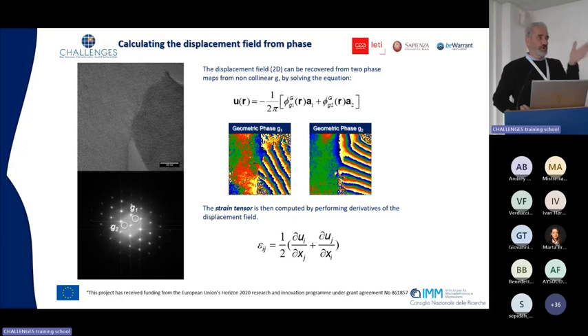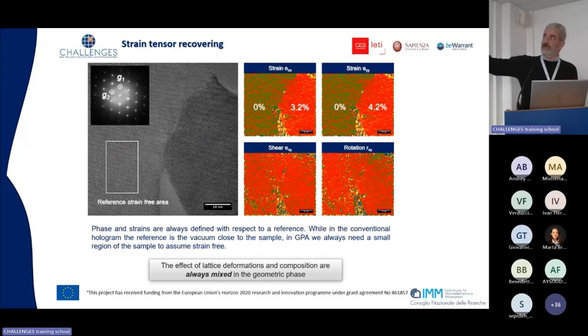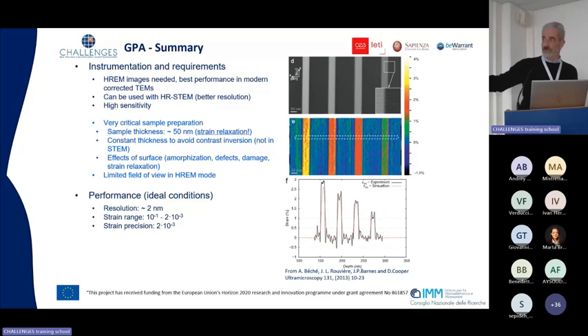So if you are able to collect high resolution images of the reference crystal and the strained crystal, you can use this method to extract the strain arrangement in your material. Okay, this is just a map representation of strain along X and Y and the shear strain, but this is straightforward. So this is from the paper I mentioned at the beginning of my talk. This is a sample composed of a multilayer of silicon and silicon germanium alloy. And this is an image in which this method is applied to extract the strain in the material.